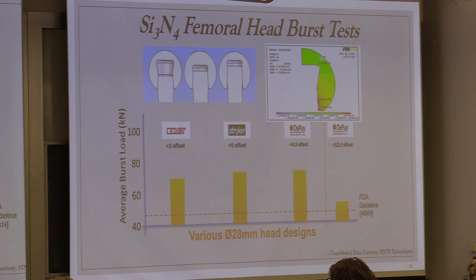But for these various offsets, there's a different stress that the ceramic can experience. And in fact, these are data for silicon nitride, unfortunately unpublished data, but they show that silicon nitride has the capability of meeting even the broadest range of offsets. So it suggests that it has very good viability as a femoral head in terms of fracture problems. And of course, I mentioned earlier that it doesn't have the degradation problem that ZTA has. So with its mechanical fracture toughness mechanism, it should last a long time.